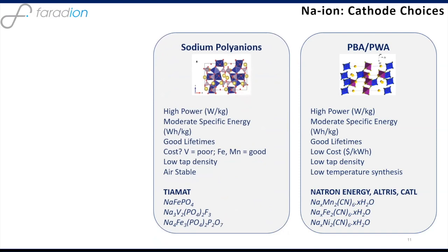The same can be true to some extent with the sodium polyanions. And Christian's going to do a great job, I'm sure, in giving you much more information on the polyanion systems. Tiamat in France is doing a great job in developing the sodium vanadium fluorophosphate material, Na3V2(PO4)2F3 cathode active material, material both Christian and I have looked at for many years. Again, this material is extremely good for high power applications. It has very good rate capability, but because it's a phosphate, it has relatively low tap density and is not always great for energy applications. But I'll draw your attention to Christian's presentation after mine.